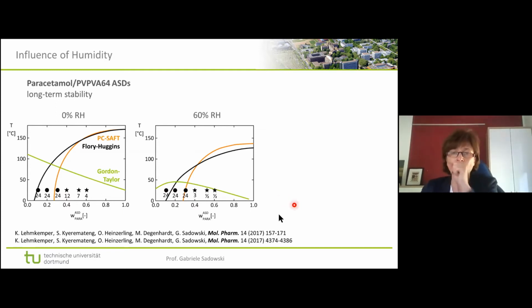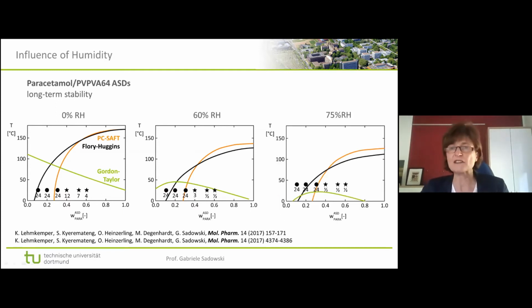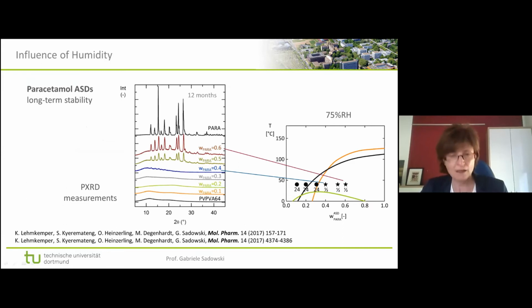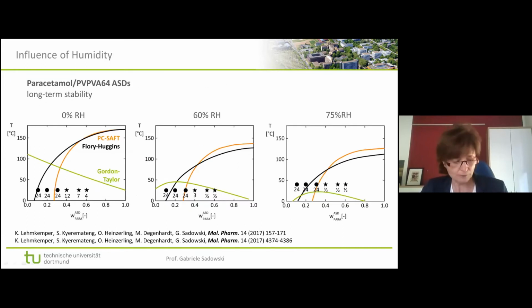And then this is 75% relative humidity. Storage is at 40 degrees centigrade. These are the so-called accelerated conditions. And what you see is now all the samples are above Tg. All samples are above Tg. So that means now kinetics doesn't help anymore. This is really only thermodynamics what we see. There's no kinetic hindrance anymore for crystallizing.